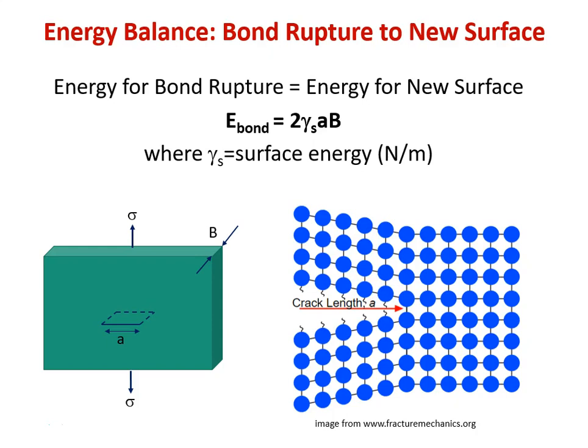So if you remember in our discussion of why dislocations are so essential to allow for deformation of materials, we discussed the energy necessary to displace an entire plane of atoms across a shear plane, and how that energy would exceed the amount of energy necessary to form a surface, and therefore would exceed the fracture energy. This is the energy to form the surface to which we were referring back then. And so that can be equated to the bond energy. So ultimately, if we have no other way of absorbing energy, we can say that the energy to propagate a crack is merely the energy to create a new surface.